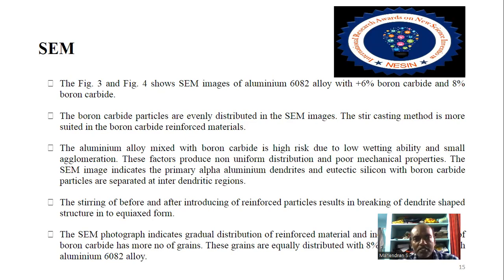The boron carbide particles are evenly distributed in the images. The stir casting method is more suited for boron carbide reinforced materials. The aluminum alloy mixed with boron carbide is high risk due to low wettability and small agglomeration. These factors produce non-uniform distribution and poor mechanical properties.